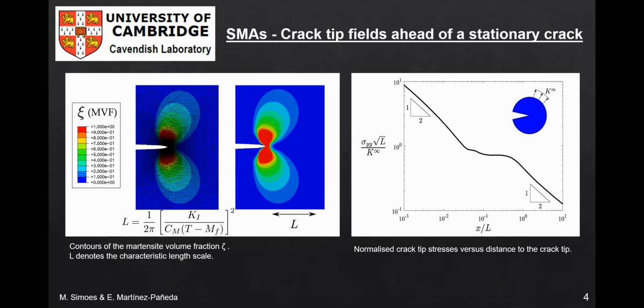On the left, you can see the contours of the martensitic volume fraction, and on the right, you can see the stress distribution ahead of the crack tip in a log-log plot. Far away from the crack tip, the stresses are governed by the austenitic material properties. Then there is a transformation zone, and close to the crack tip, the material is fully martensitic. And the key thing is that this stress-induced transformation brings some toughening of the material.